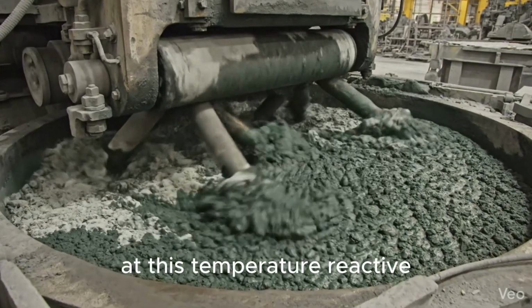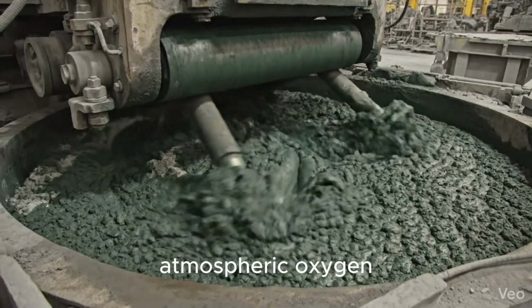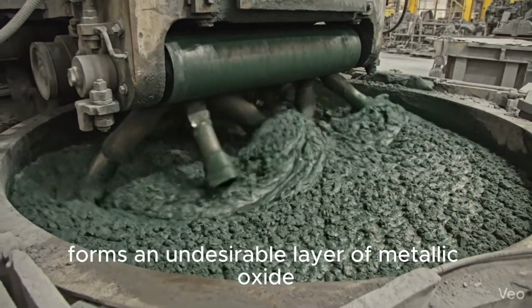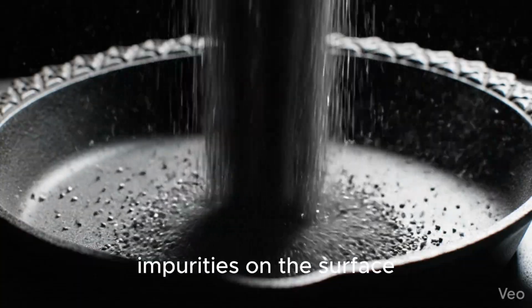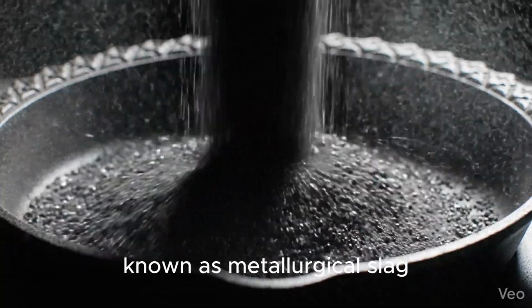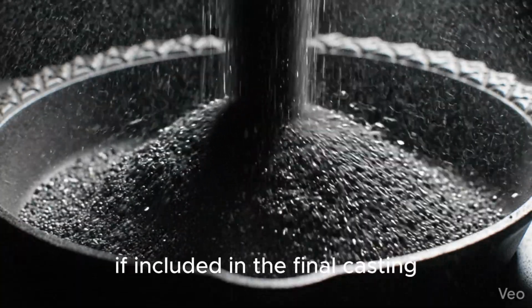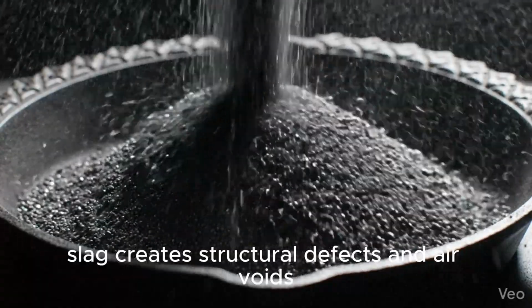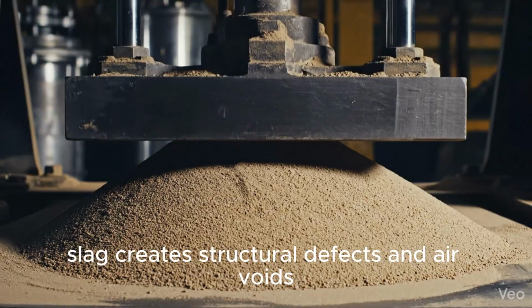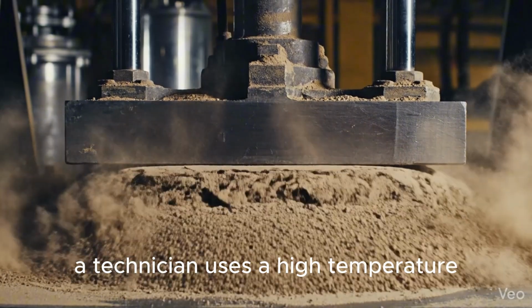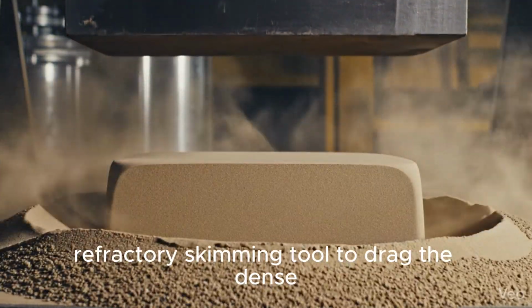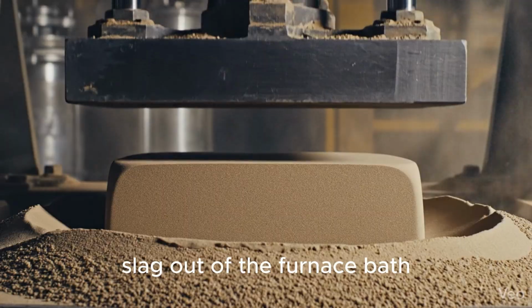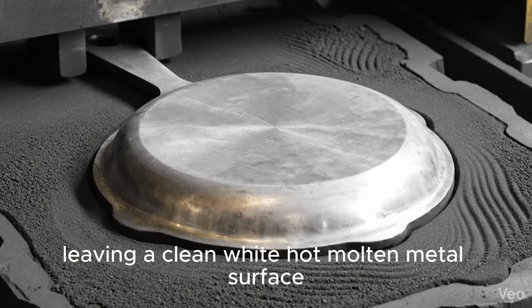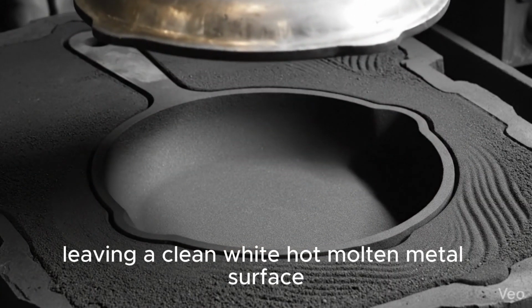At this temperature, reactive atmospheric oxygen forms an undesirable layer of metallic oxide impurities on the surface, known as metallurgical slag. If included in the final casting, slag creates structural defects and air voids. A technician uses a high-temperature refractory skimming tool to drag the dense slag out of the furnace bath, leaving a clean, white-hot molten metal surface.